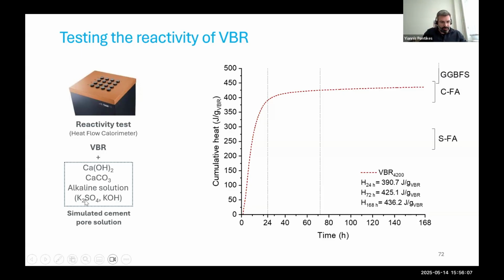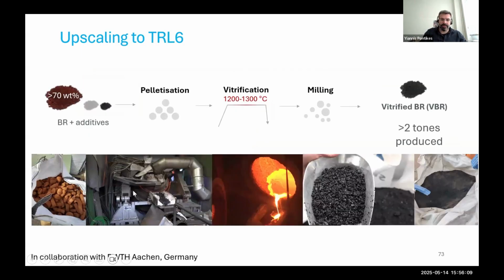And that's what you do. That's what you add with the VBR in this case. Then we've done upscaling. This happened in Aachen in their TBRC furnace. We made, I think, close to 4 tons, out of which 2 point something eventually came back to Belgium, and we made products out of them.